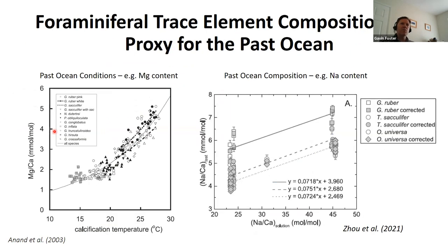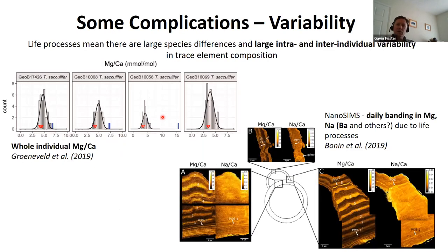So if we go back to this calibration, 3 to 6 would suggest that the forams are living at anything from 20 to 30 degrees, which is not true, because we know they're all living in quite a narrow range. This is just because of life processes changing the way in which magnesium is uptaken by the organism. That actually varies between different individuals of the same species. So the average gives a meaningful correlation with the calcification temperature, but there's a lot of spread for the individuals.